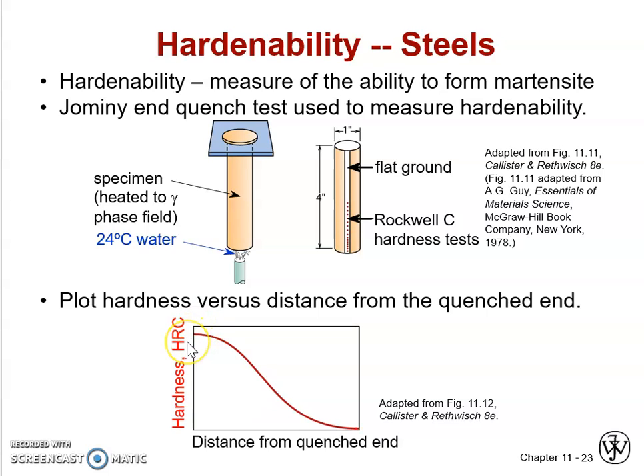Okay, so from this part you will get high hardness, and by increasing the distance the hardness will reduce. If you plot the graph, you will get the high hardness at this point near the quench end, and as you increase the distance from the water jet, the hardness will reduce. You got what I mean? Okay, so here the hardness is high. As the distance increases, the hardness will reduce because the time for the steel to cool is long. It will not form martensite, because if you want to form martensite, the cooling should be very fast.